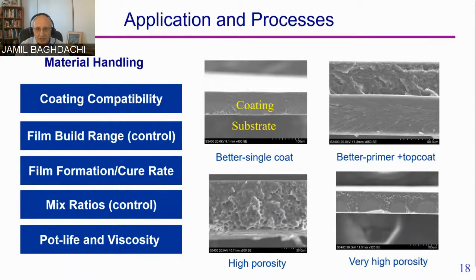Almost 50% of the coating, as you can see, has porosity in it, holes in it. Imagine that water passes through the system, which it does, and falls inside those holes. As you can see, it produces vacuum. It also turns into a vapor, right? Expands, contracts, freezes inside those holes. This is why it happened to the airplane, because when it came back after the maiden flight, after everything's done, the airplane goes up and takes a flight, right, for practice. By the time it came back, it looked like a tiger, because some of the paint actually peeled off because it had all these holes in it.